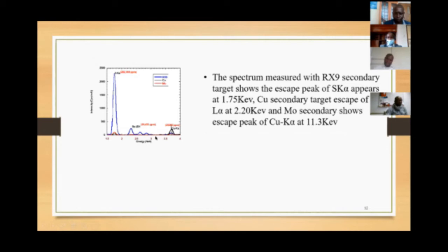From the sample, we are also able to see that sulfur was present at 282,000 parts per million, antimony at 69,400 parts per million, and copper at 23,000 parts per million. Therefore, from EDXRF, the sample that I prepared contains copper antimony sulfide in that ratio. So it was copper antimony sulfide, actually, the thin films that I prepared.